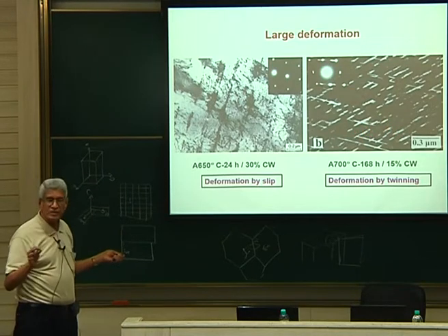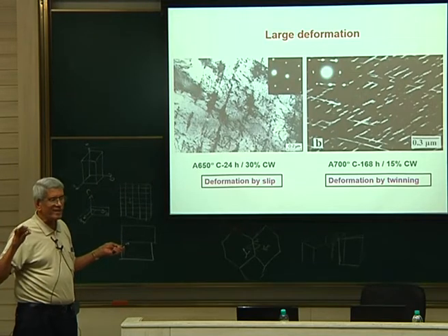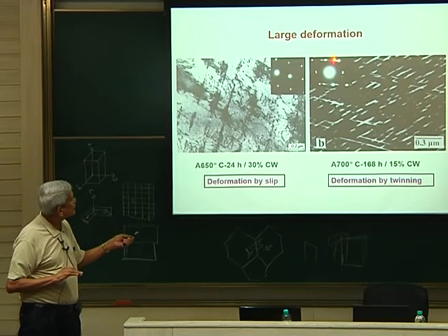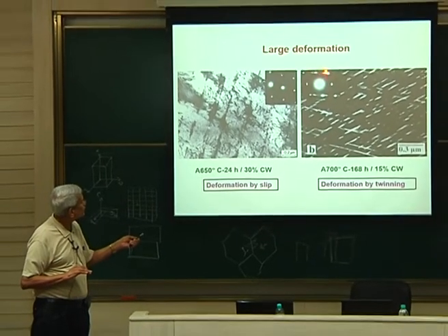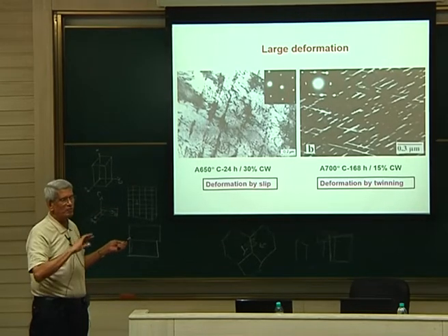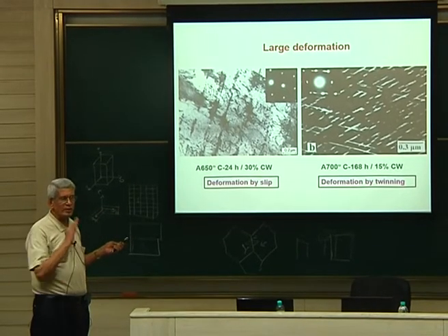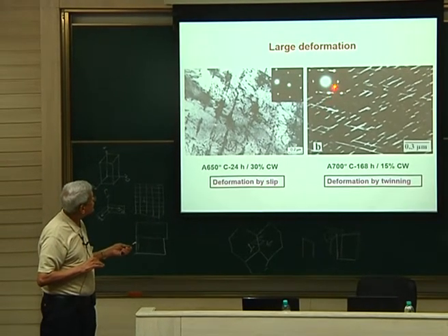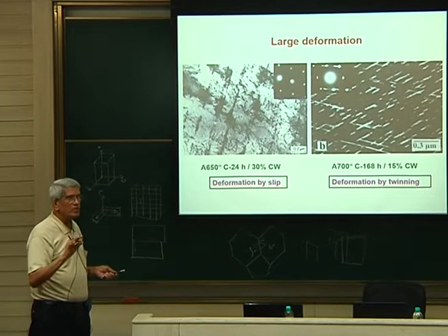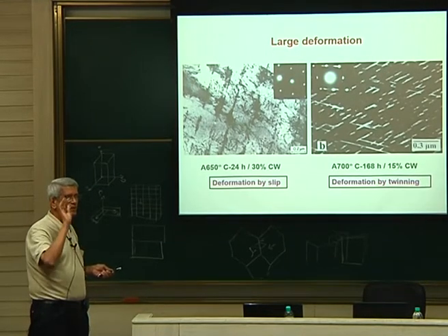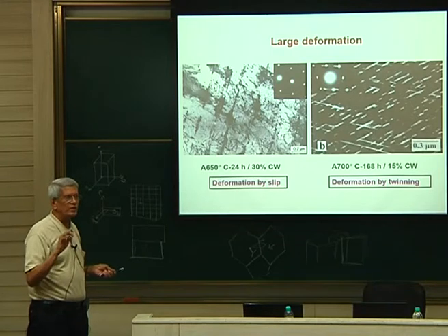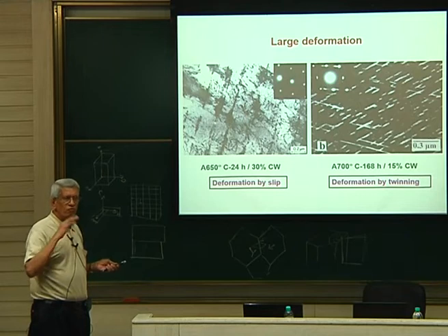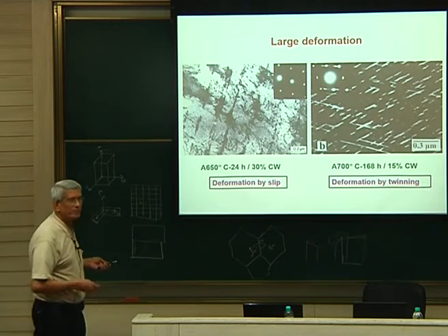And as I mentioned in the last class or the earlier class, how to identify the twins. Now you can see that there is a twin reflection. This is the twinning plane, across which all these reflections are getting a mirror image of the diffraction pattern. This is the way we can identify it. In addition, this reflection also gets reflected to this one, which is an indication that the order is being maintained in the twin lattice also. That is why we call these true twins. If the order of the lattice is not maintained, we call them pseudo twins.